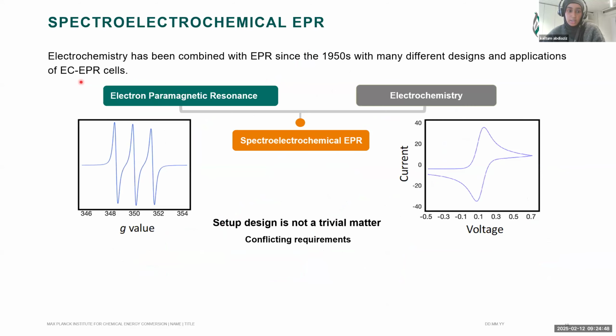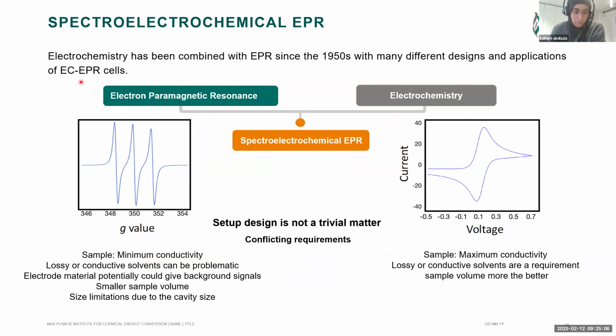So I hope I showed you that these two techniques are a great pair together to get as much information as you can from your redox reaction. However, the problem comes from their conflicting requirements. In EPR, you want to minimize or at least avoid any conductivity in your system. So lossy samples and conductive solvents are a problem because this interferes with your microwaves. And the electrode material, since you are generating your species of interest at the electrode, can influence or affect your ability to measure EPR.